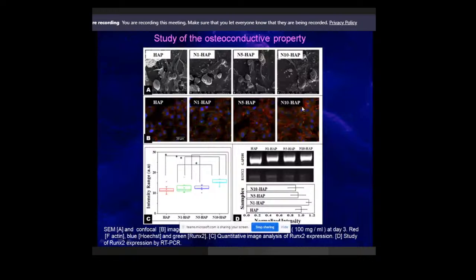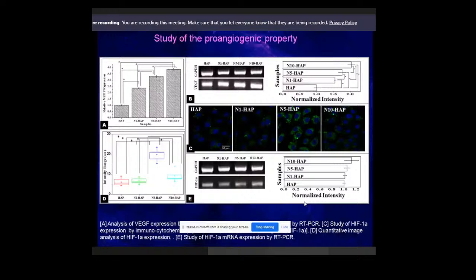Similarly, we also checked the expression of certain factors. This green one is RUNX, a differentiation factor of this particular cell, and we checked the corresponding expression. We also checked these things through RT-PCR, and then checked the proangiogenic property of the material. Here we observe that the moment we dope the nickel, the relative VEGF production by the cells increases manifold. You can see a huge and continued, dose-dependent increase in VEGF production.